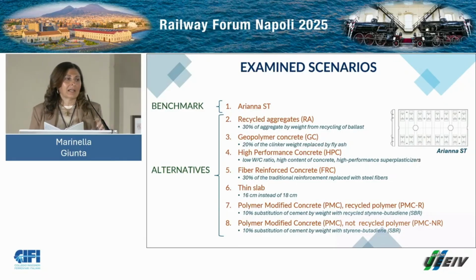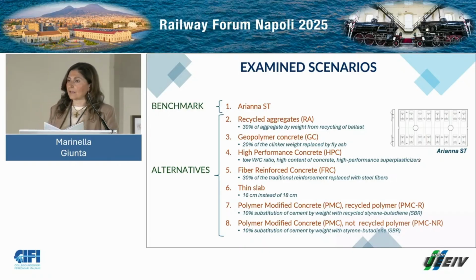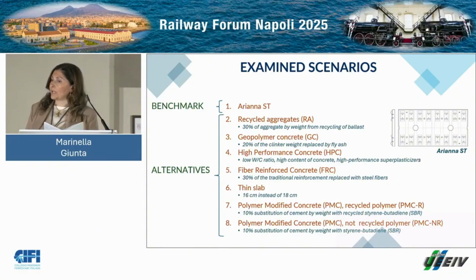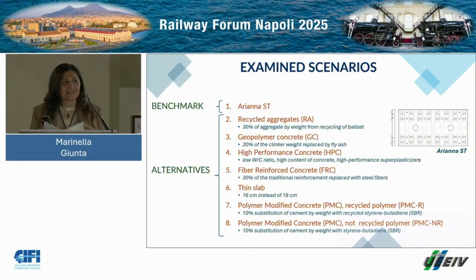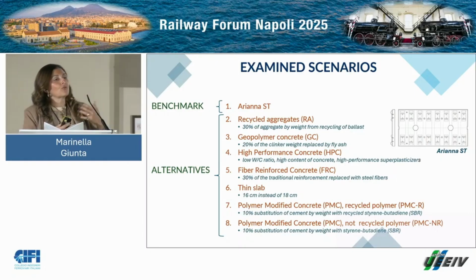The thin slab, a slab with reduced thickness, 16 centimeters instead of 18, and the polymer-modified concrete with recycled polymer. This is a scenario in which 10% of cement is substituted by recycled SBR. And another scenario, the same polymer-modified concrete, but with virgin polymer, in order to assess the improvement from the recycling of the polymer.